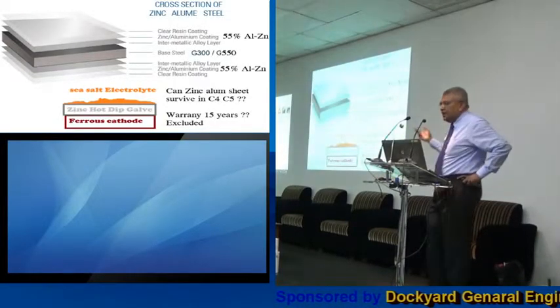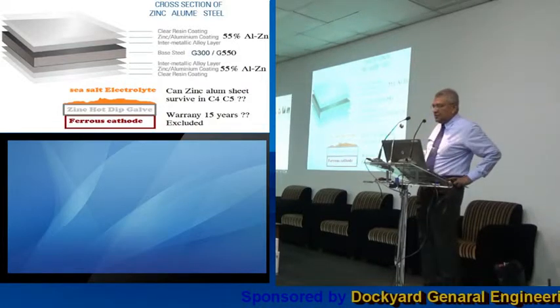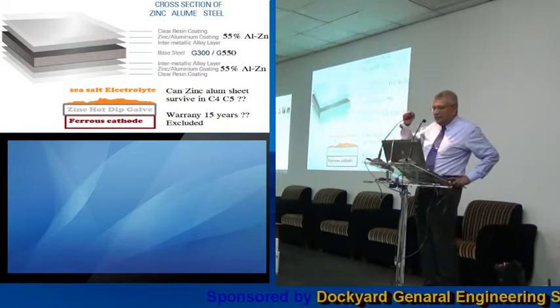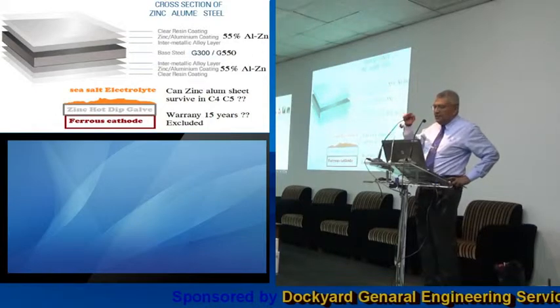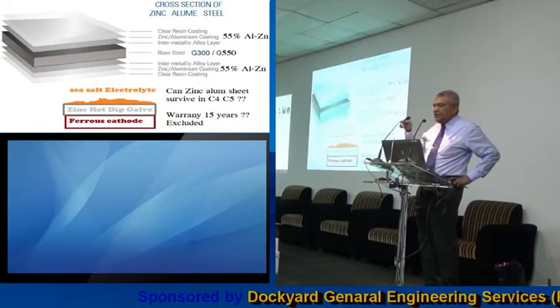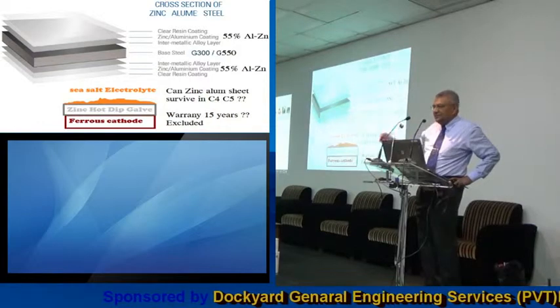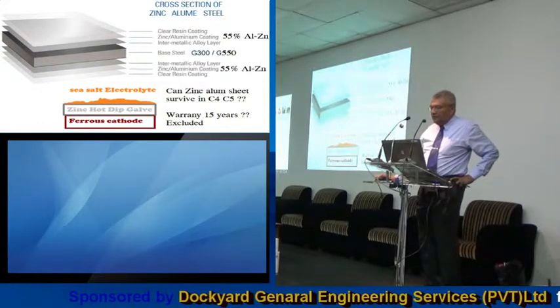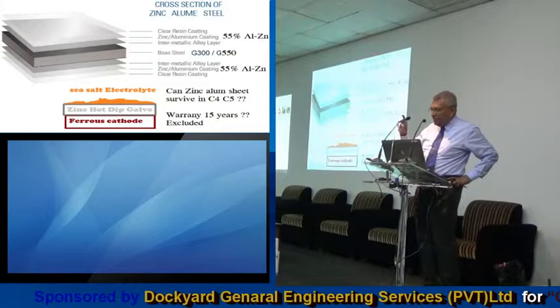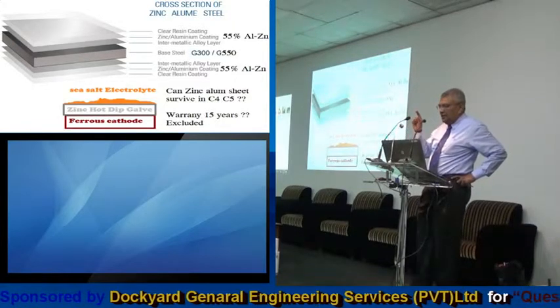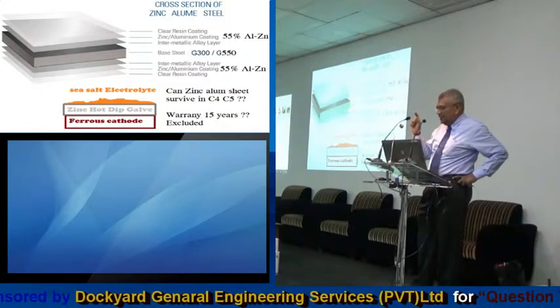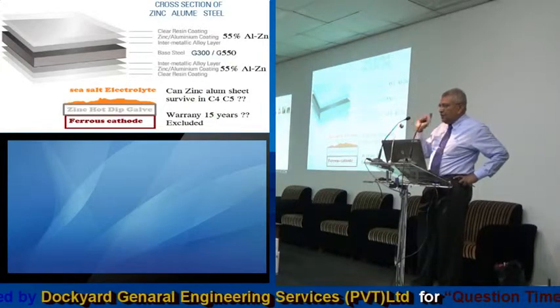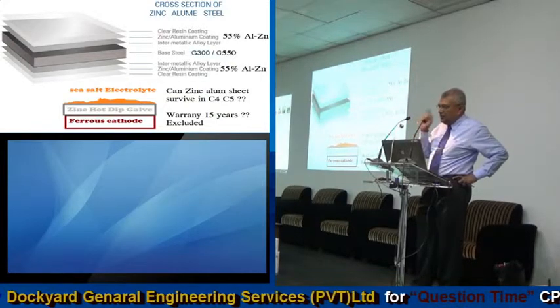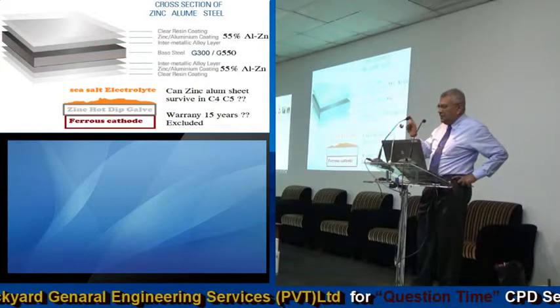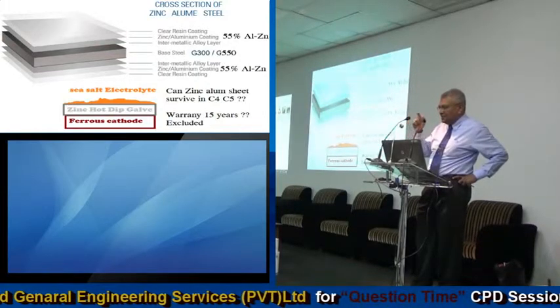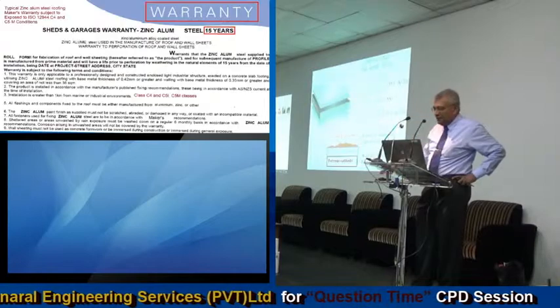Now you take the zinc alum sheet. Now zinc alum sheet, you take cross section. You have a zinc base, then there is an intermetallic alloy layer, then zinc alum coating, then the clear resin coating. Clear resin coating is just an eyewash. So now the base metal steel is ferrous cathodic. The zinc alum is anodic. So you fix it in a mild environment, no problem. You fix it in a moderate one, no problem. But you fix it in Gulf face, C4 C5, you are in heavy trouble.